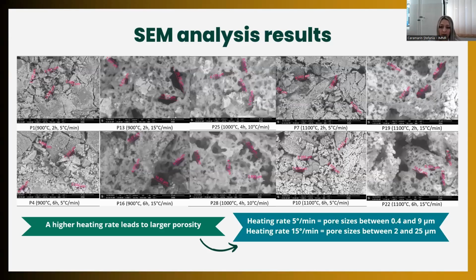The SEM results. In the SEM images, we looked mostly for the porosity, or the forms and size of the pores, and we concluded that a higher heating rate leads to a larger porosity. If we compare 2 images, for example, at 900 Celsius degrees, with a heating rate of 5 Celsius degrees per minute, we obtain pores with sizes between 0.4 and 9 micrometers. But for the samples with a heating rate of 15 Celsius degrees per minute, we obtain pore sizes between 2 and 25 micrometers.